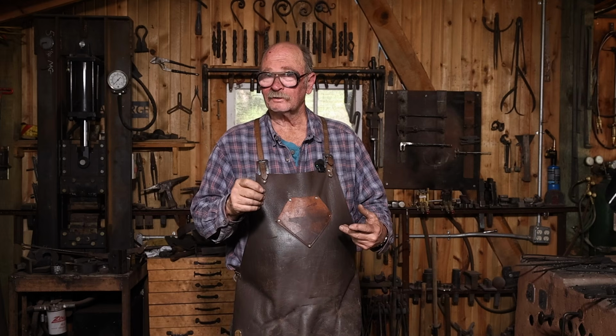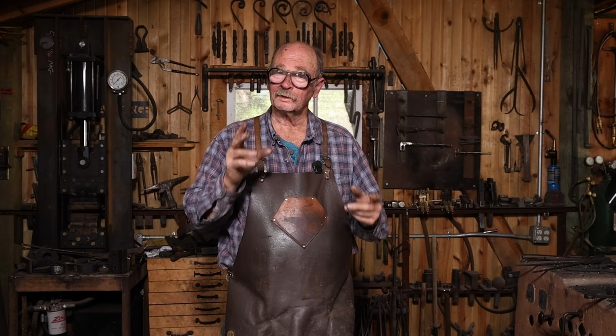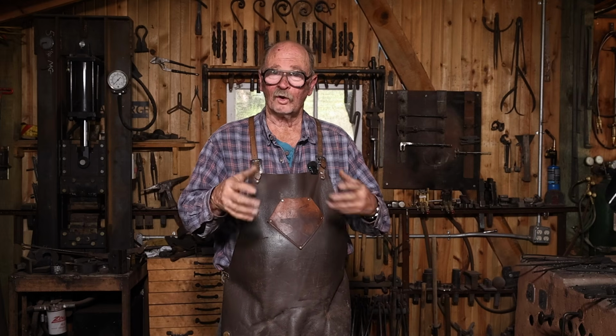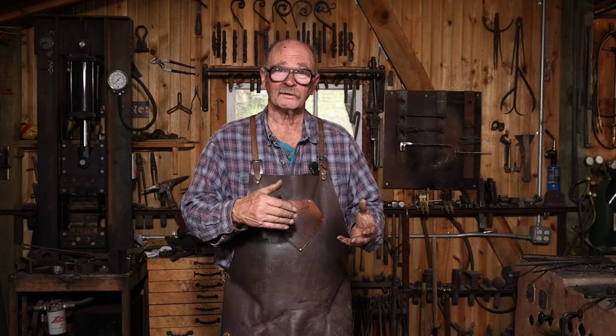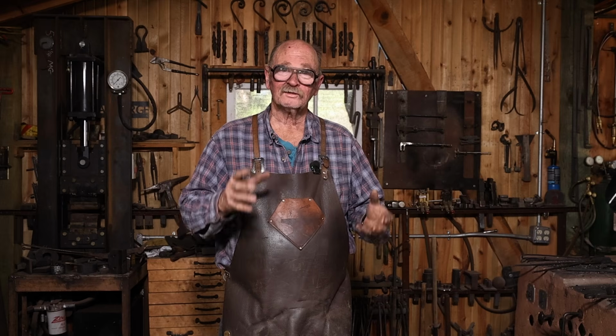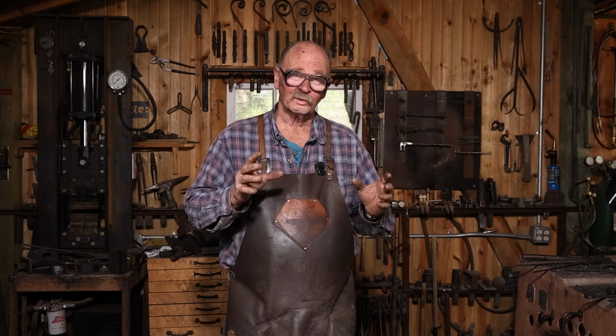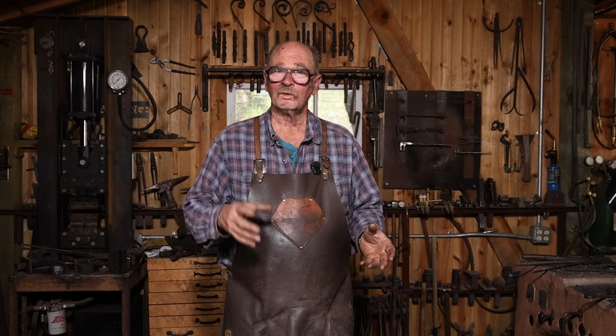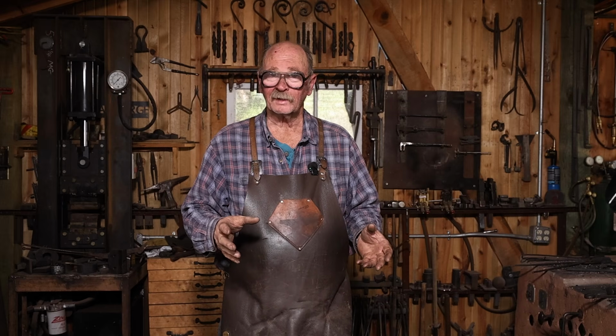The other big downside to welding with gas forges, if you're welding with flux, and for most open welds, you need flux in a gas forge, the flux eats the lining of the gas forge. It's really hard on the ceramics, and you will wear your forge lining out much faster.